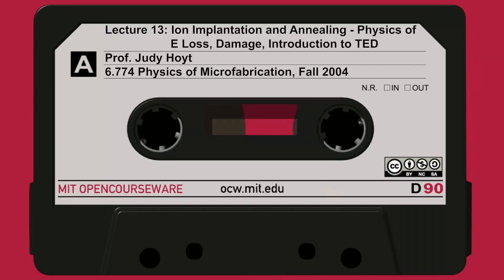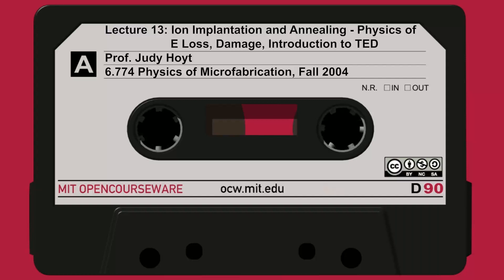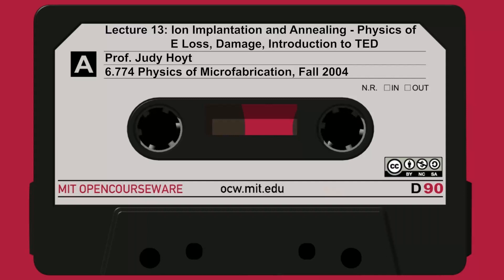Look at the binding energy of a silicon atom on the lattice — that's only 15 electron volts. So you can imagine that we're coming in with a species that has thousands of times more energy than the binding energy. It's quite possible to have billiard ball-like collisions where you knock these silicon atoms off of their lattice sites. The ions collide elastically, resulting in ion deflections where the ions change their direction. When you collide, you lose a certain amount of energy. The ion loses some energy and it displaces silicon atoms, which we end up calling recoils.